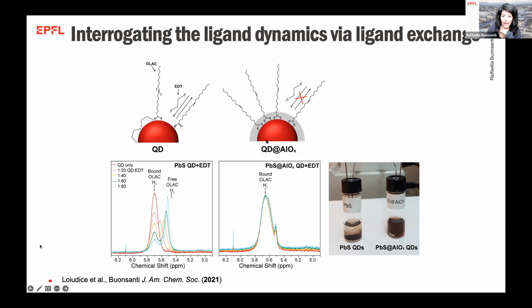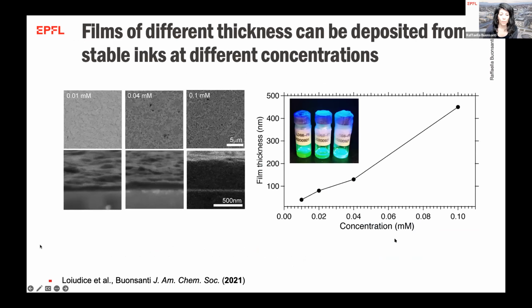Now, it was clear as we did this test in the presence of the aluminum oxide shell that the exchange does not happen and the solution remains stable. And we were also able to demonstrate that we can make really highly concentrated inks, and these inks remain stable, and that allows us to obtain very thick films, which are 500 nanometers in one deposition, while normally you need to multi-layer diluted concentrations to get to this point.